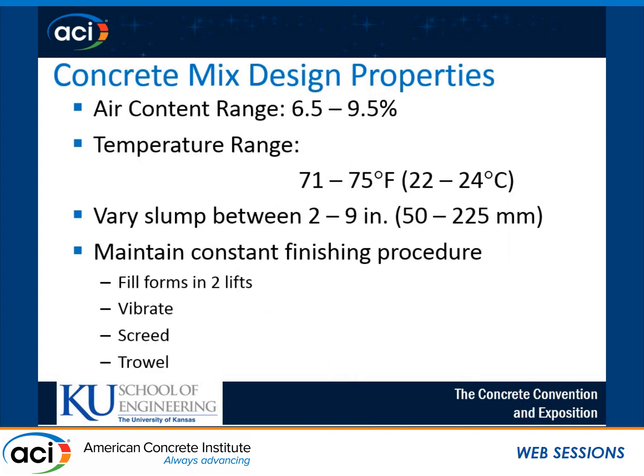So for the properties that we're looking for in our concrete mixes before we actually cast specimens, we want an air content between 6.5% and 9.5%, concrete temperature between 71 and 75 degrees Fahrenheit, and then our independent variable that we use in these studies is the slump. So most of our series vary the slump between 2 and 9 inches.